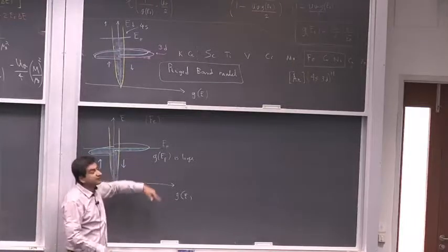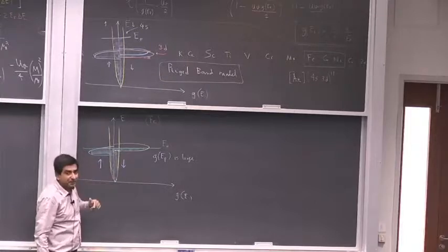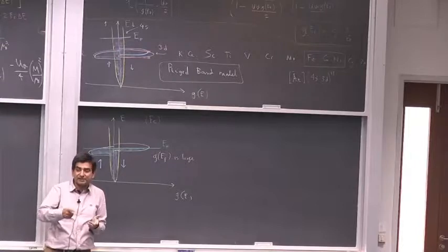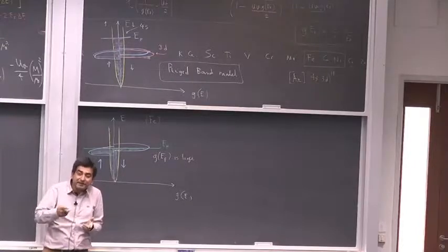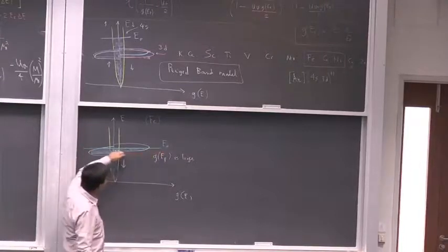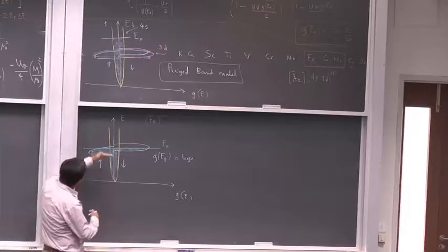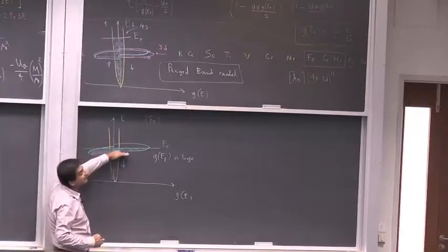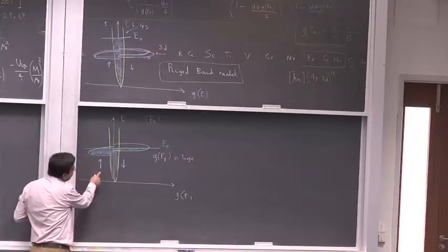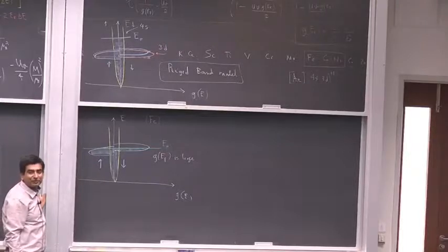And if the density of states at the Fermi level is large, then you can expect the Stoner criterion to be satisfied. So this really means that the Fermi level intersects with the 3d band. And now one of the bands lowers its energy, the other band raises its energy because of the Stoner criterion. Now you have more spins of this kind than of this kind. Alright?